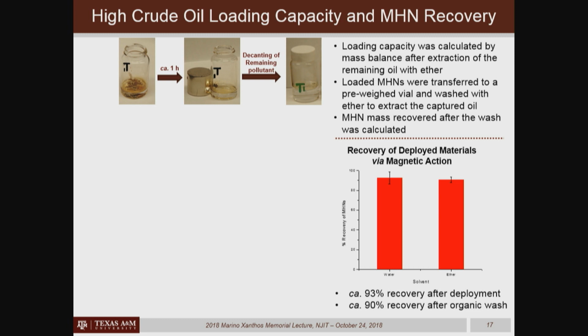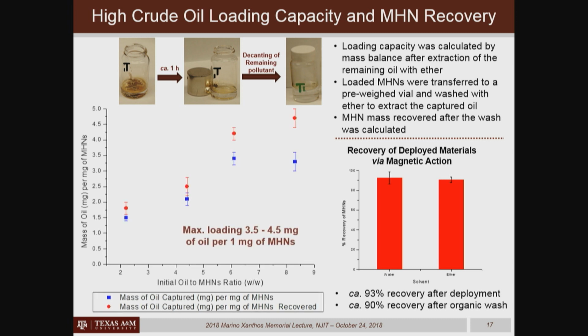And here you can see some actual images of the lyophilized powder of these magnetic hybrid network materials as Jenny dropped it into the vial. And then after a period of time, you can see that she's collected the oil-filled particles, and there's some crude oil here that you may be able to still see floating on the surface. And then she analyzed the residual solution for the amount of crude oil that had not been captured by these magnetic hybrid networks for their quantification.